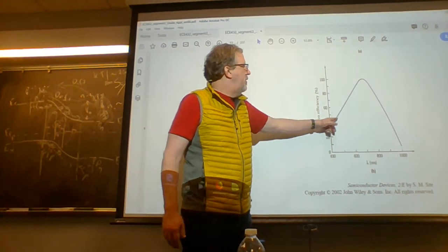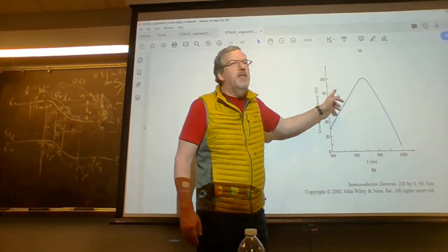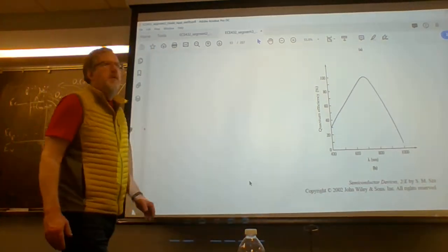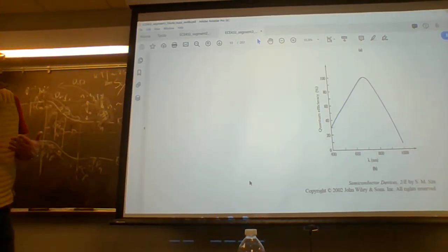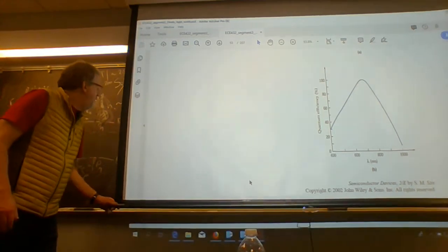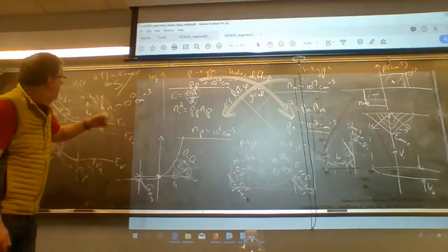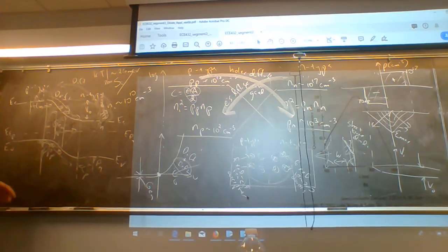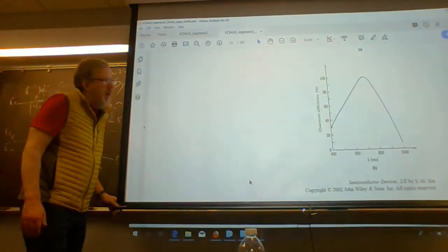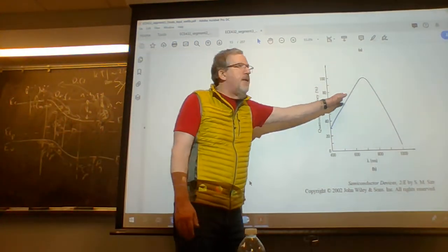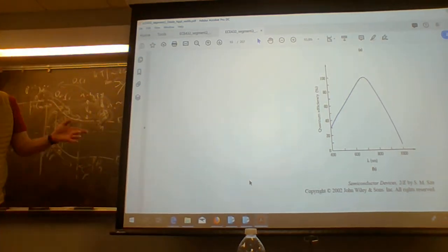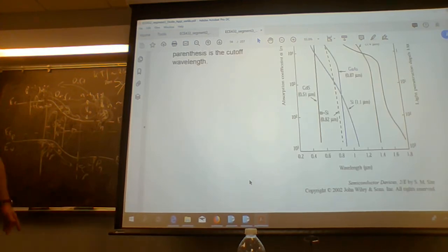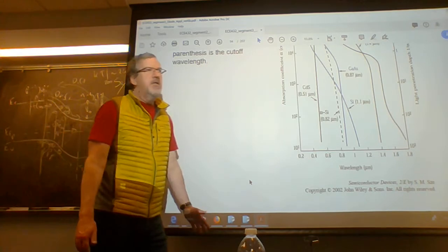And here, the energy is getting higher and higher, so what's happening to the photodiode? The collection is getting tighter and tighter towards the top. So it's coming in and it's being absorbed closer to the surface, alpha is getting very high, so the collection is happening near the surface. So now the surface recombination and all those dangling bonds start to suppress it, so the carriers might not even get across the PIN junction. And we talked about this. The shoulders are due to the indirect band gaps, the participation of the phonons.